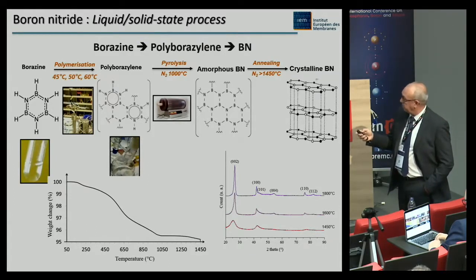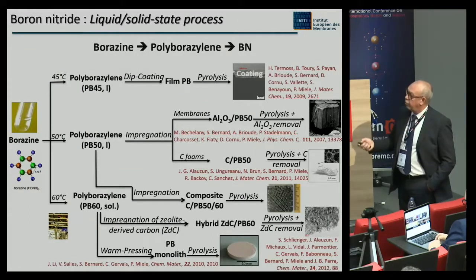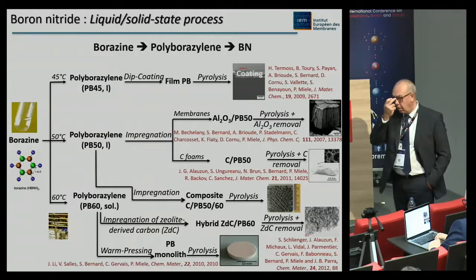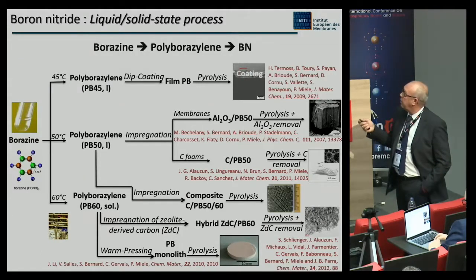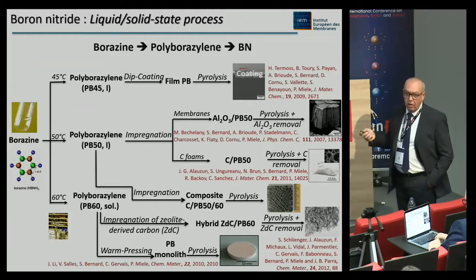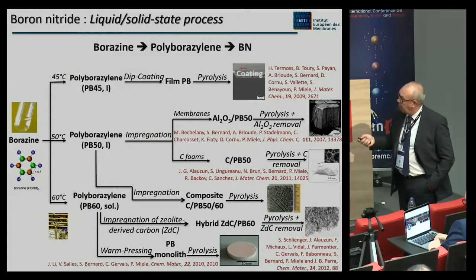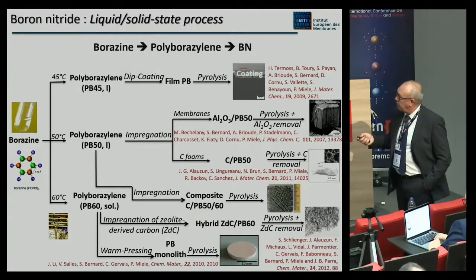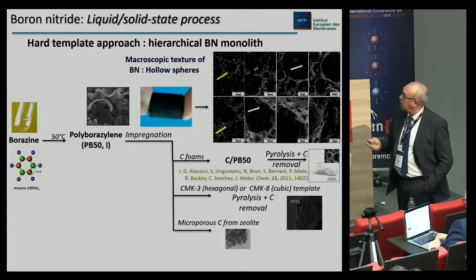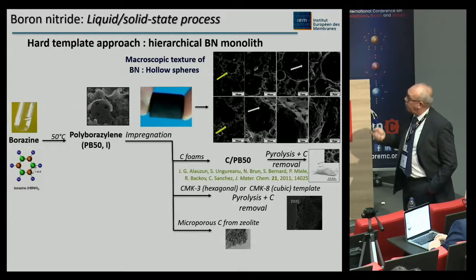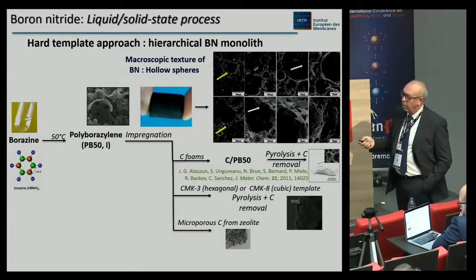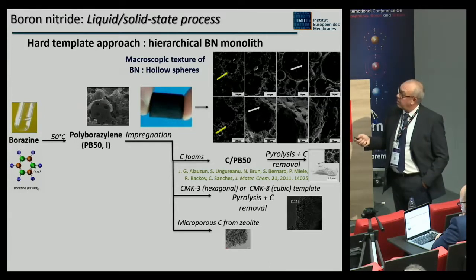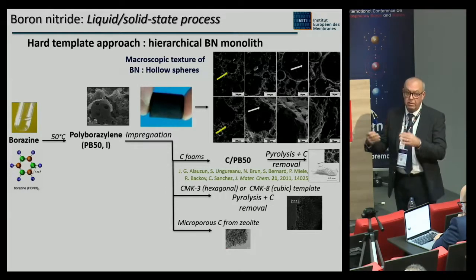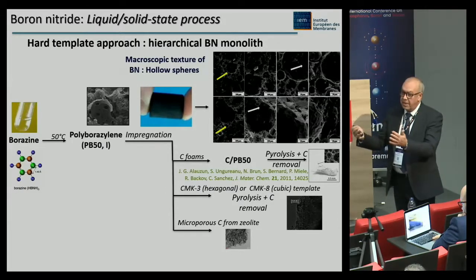Using this precursor, it's possible to prepare a lot of structures that we have done in the group: coatings, membranes, composites materials, zeolite-like porous materials, compact monoliths, dense monolith, and so on. And also, I will just focus on this particular porous materials today, starting from borazine, which can be polymerized at 50 degrees. We obtain this polyborazylene, and by impregnation, the method is relatively easy, but the same that I had already described.